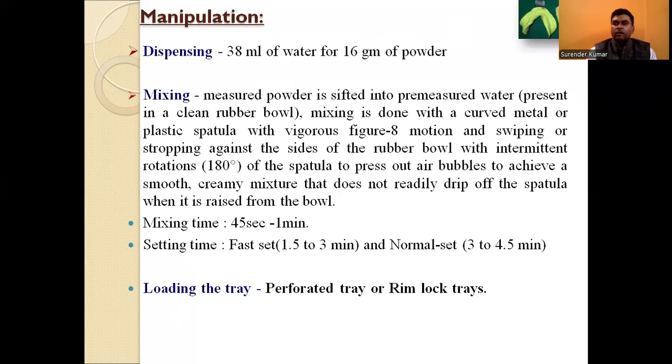Manipulation: you can manipulate that in 38 ml of water for 16 grams of powder. A measured amount of powder is sifted into a pre-measured amount of water that is present in a clean rubber bowl. Mixing is done with a curved metal or a plastic spatula with a vigorous figure-of-8 motion and swiping or stroking against the sides of the rubber bowl with intermittent rotation.